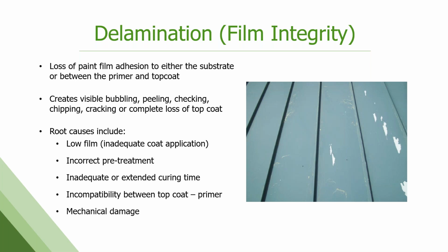Okay, so delamination or film integrity, the other thing that's covered under warranty. This one gets really tricky. This is loss of paint adhesion either to the primer or to the substrate. You can get visible bubbling, peeling, cracking, chipping, however it presents. I've listed the top five reasons this happens, but there's about a million other reasons why you might get delamination of a paint system after installation, which makes this a really hard one to investigate. But the common ones are low film, maybe an incorrect pretreatment that was used,